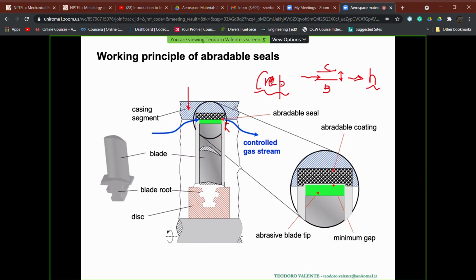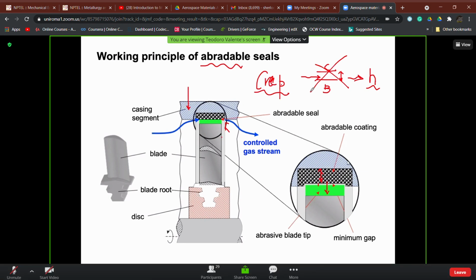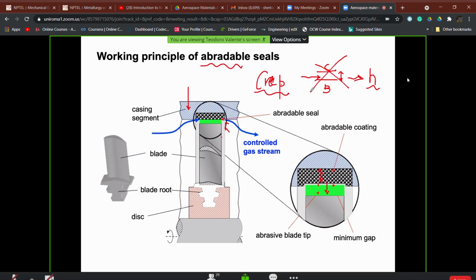A solution is adopted which is based on the use of abradable coatings, which can be put on the casing, for example, by using an abrasive blade tip, that is another coating, so that this coating in correspondence with the end of the blade tip can be easily consumed during the working lifetime of the engine, assuring the minimum gap which is able to maintain the rotation of the blade, but cancelling this mechanism for which we will not be able to convert the energy coming from the combustion in the combustion chamber of the engine to mechanical energy, which is given by our turbine.